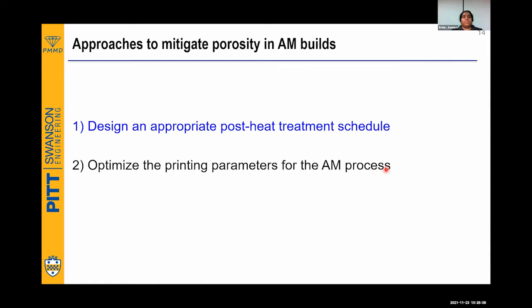So when I project these two solutions, it is kind of common sense to say that yes, before you start printing, just optimize the printing parameters for the AM process, and then you build all your tensile bars and so on. But we need to understand the fact that in many cases, we won't have enough powder. We are not always having kilos and kilos of powder which we can lavishly use. Sometimes the amount of powder available with us might be pretty low. If that is the case, to optimize the printing parameters, what we generally do is we build cubes with different printing parameters, like different scan speed and laser power, and we print the cubes, find the porosity levels using Archimedes, and do a second level of checking with the closed pores, and then we figure it out. But we don't always have the liberty to do that.